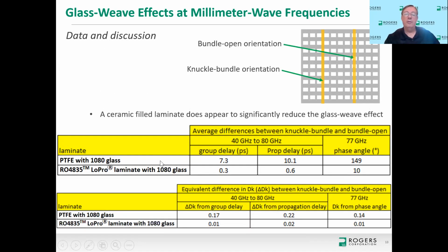So the first row of information is really the same information I showed two slides back. And that's the pure resin system with 1080 glass. That's PTFE and 1080 glass, 77 gigahertz. I get a phase angle of 149 degrees. And that same configuration with highly filled ceramic, that is 4835 low pro laminate with 1080 glass.